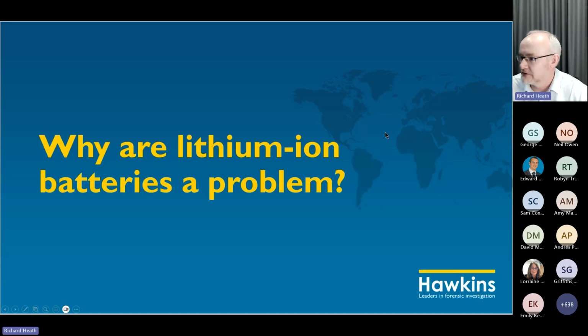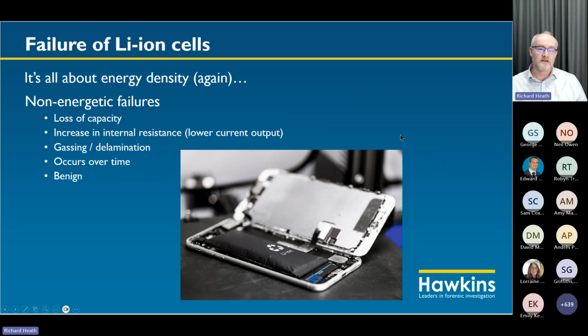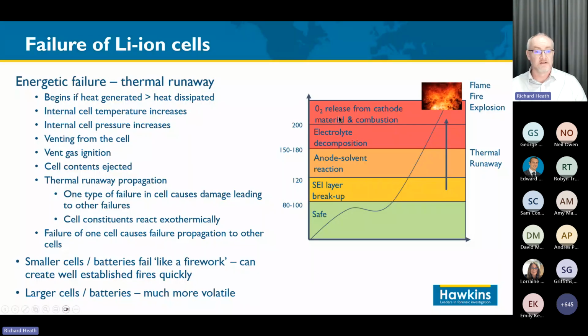So why are lithium-ion batteries a problem? Well, it's all about energy density again. And I want to emphasize that lithium-ion batteries don't always go bang. A lot have non-energetic failures, and you may have experienced some of these yourself. And this is where the cell has a loss of capacity. The internal resistance of the battery increases. Sometimes you can get delamination or gassing, and that's what's shown in the picture here. We have a mobile phone that's popped open because the pouch cell, flexible cell, has expanded as the battery has failed. It's a process that occurs over time, and it's benign, so nothing more dramatic happens, although it's very inconvenient.